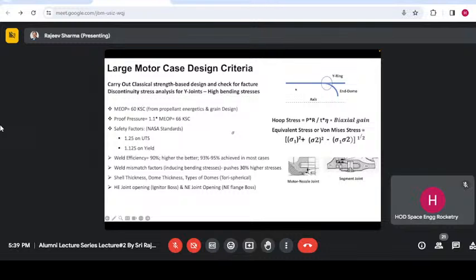Now, our sheet thickness for the shell and the sheet for the domes were the same thickness. We accounted for the thinning of the sheet at the dome during fabrication and forming, but it did not actually thin that much. And so we landed up with a very large weight, which was not even designed. The design thickness of the dome was at some level, and I had more than 10% extra thickness, which was absolutely not tolerable. I remember getting such a scolding from Dr. R.N. Agarwal: how the hell did you not even think about it? And quite honestly, I had not. I assumed that the material would thin by that dimension based on the fabrication details.